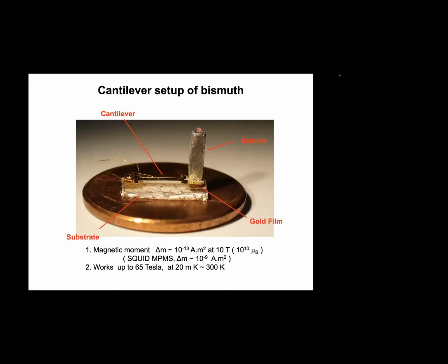So this is the principle. This is a simple picture of the design. This is not the actual sample. The actual sample is much smaller than this, but it's a very early picture that I took during my graduate school studies when I had a bismuth sample sitting on a floppy cantilever, and the cantilever is standing up. I have a small gap between this metallic cantilever and a gold film underneath. So I have a teeny tiny gap there. And then I have two metals that form a capacitor. And by tracing the capacitance and magnetic field, I know the deflection.